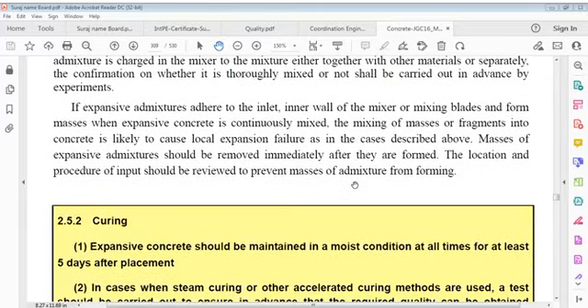If expansive admixtures adhere to the inner wall of the mixer or mixing blades and form masses when expansive concrete is continuously mixed, mixing of masses or fragments into concrete is likely to cause local expansion failure, as in cases described above. Masses of expansive admixtures should be removed immediately after they are formed. Location and procedure of input should be reviewed to prevent masses of admixture from forming.